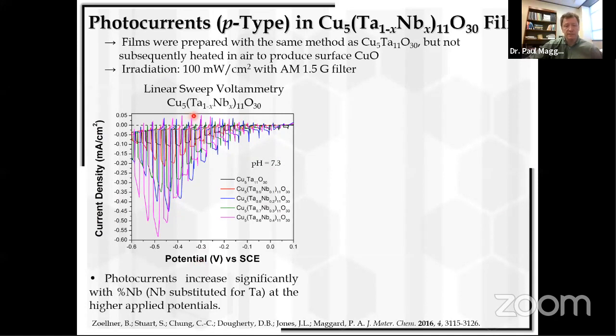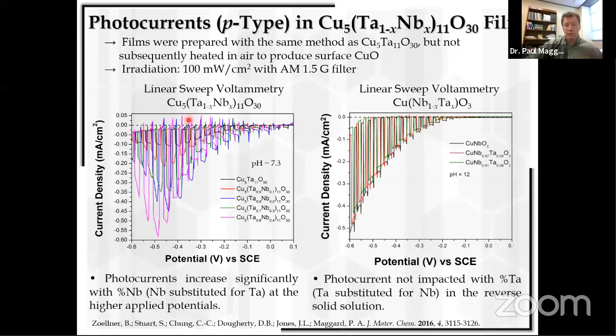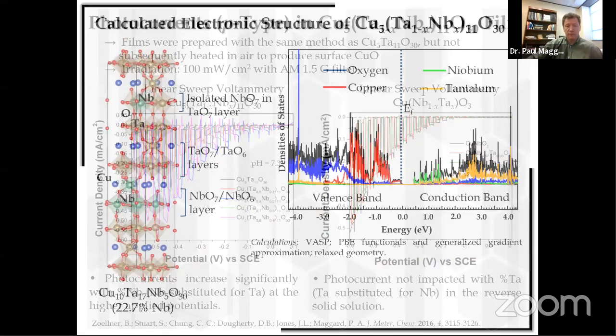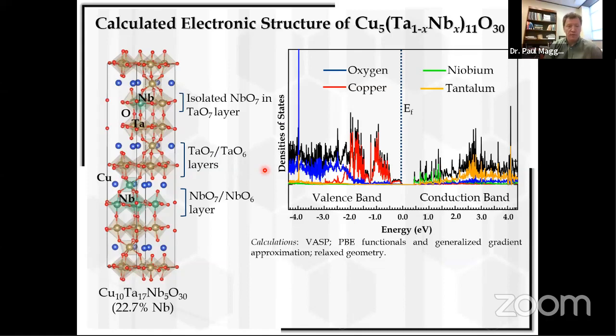This is unusual, because if this is a very disordered crystalline structure, you would think there would be a lot of trapping and disorder, and the carriers would not be able to reach the surfaces very efficiently, yet they do. If we do the reverse solid solution, though, we see no synergistic effect. In other words, if I take a copper niobate and I mix tantalum into it, I see no improvements in the photocurrent. In fact, they stay relatively constant no matter how much tantalum I put into it. Okay, that's the reverse solid solution. So let me explain why, in a solid solution, you could still observe this carrier movement throughout its network.